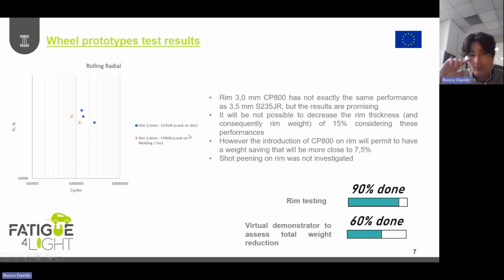After the disk, we tested also the rim. The tests for the rim are not yet finished to 100%. In any case, on the rim, the situation is a little bit different. The 3 millimeter CP800 compared to our normal rim S235 JR has lower performance. But we can say that with this material, we cannot reduce the weight and the thickness by 15%, but by 7.5%.